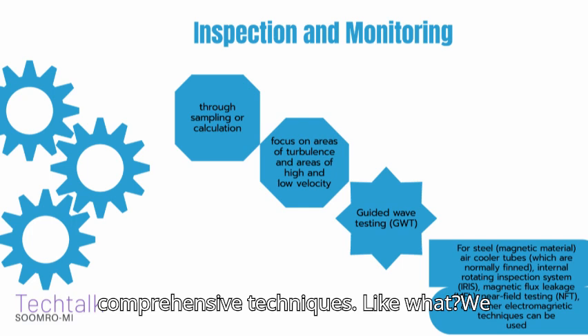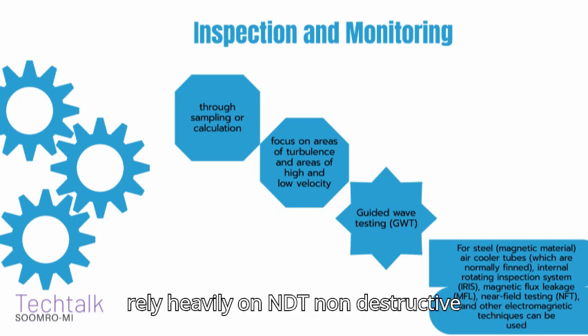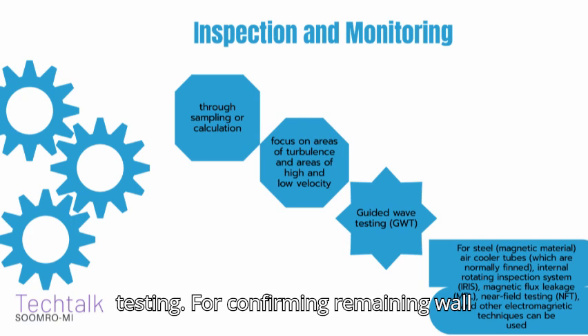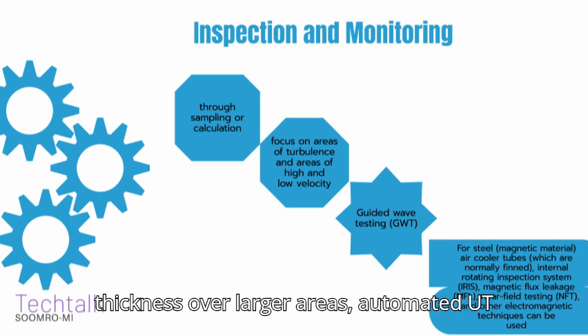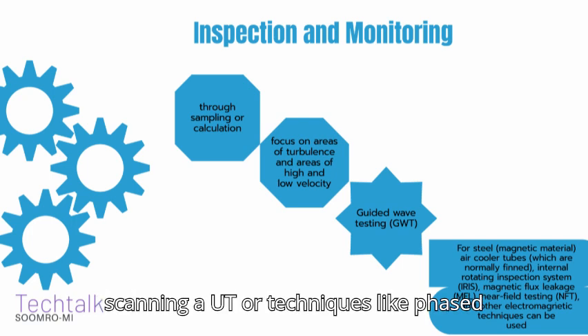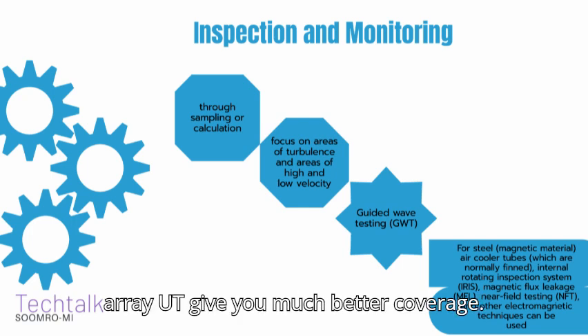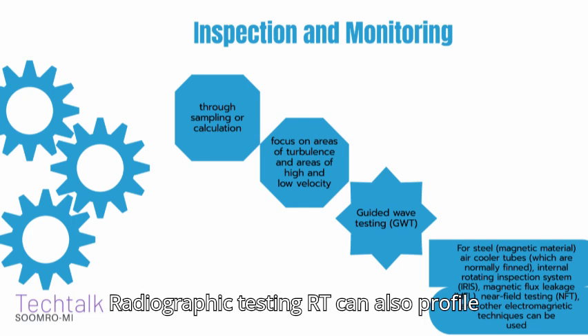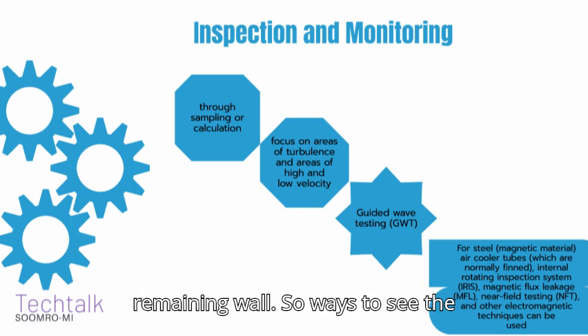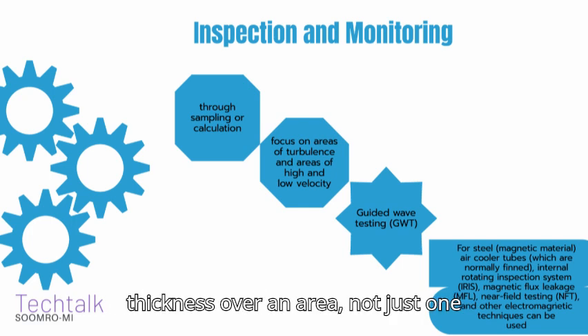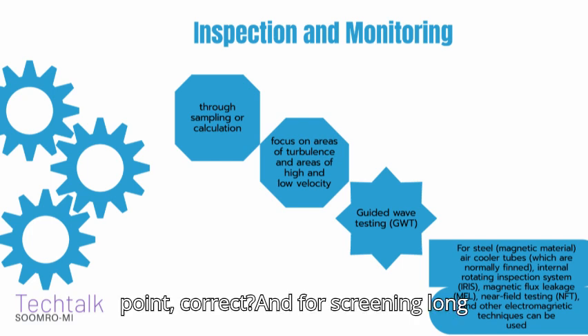Like what? We rely heavily on NDT, non-destructive testing. For confirming remaining wall thickness over larger areas, automated UT scanning, AUT, or techniques like phased array UT give you much better coverage. Radiographic testing, RT, can also profile remaining wall. So ways to see the thickness over an area, not just one point. Correct.